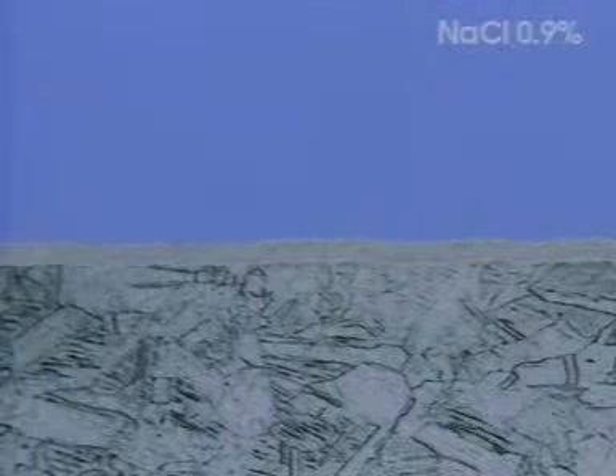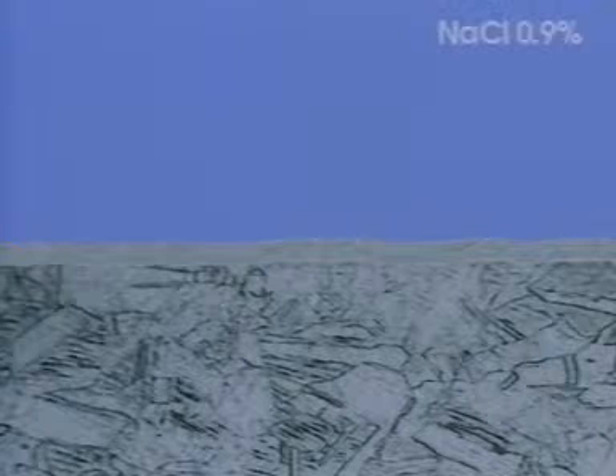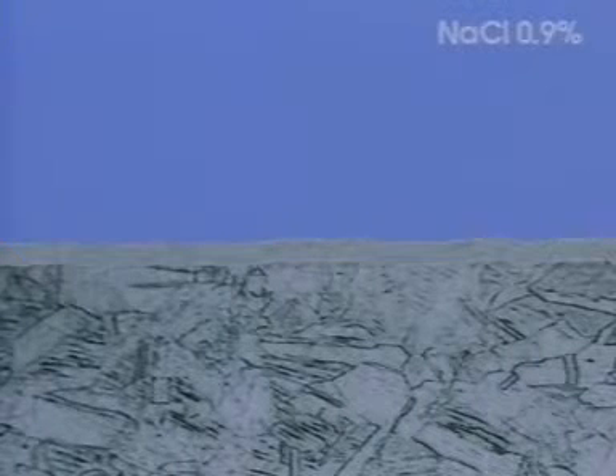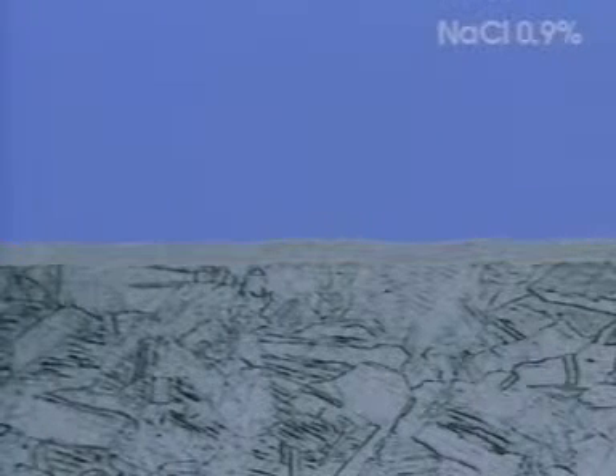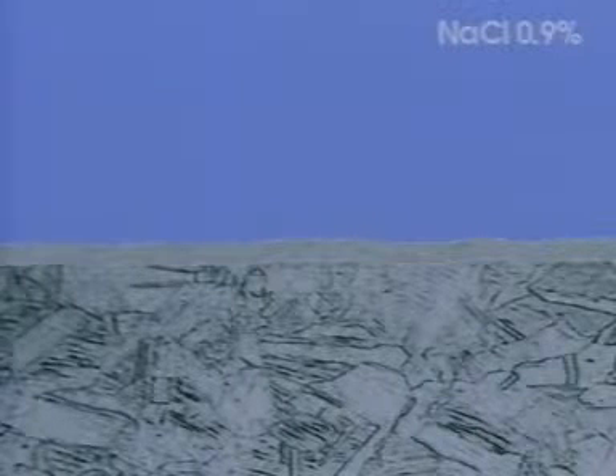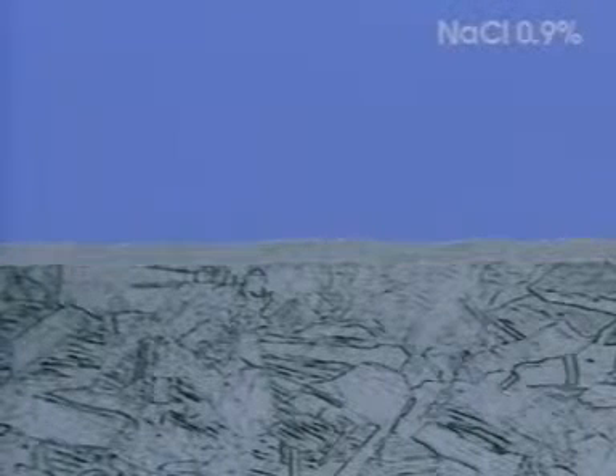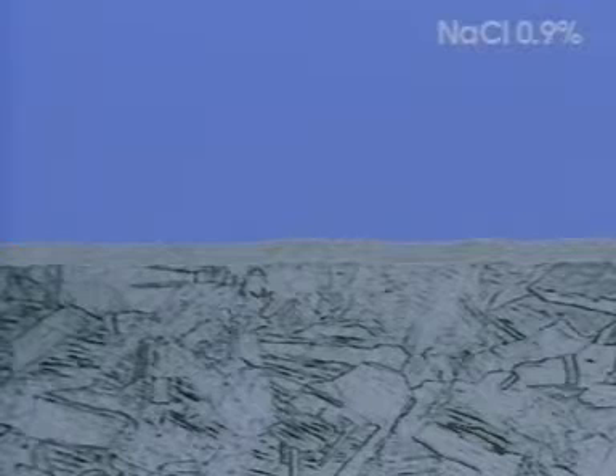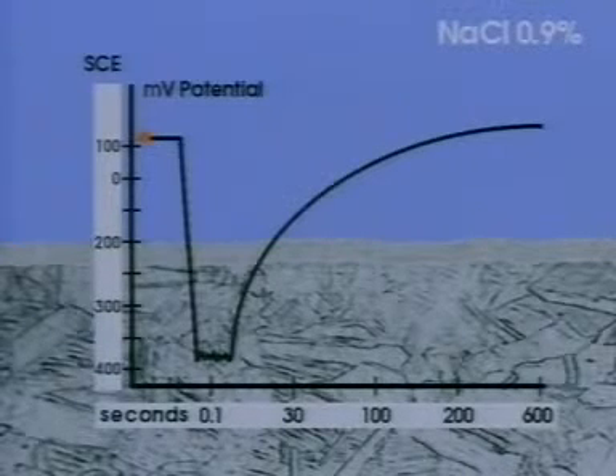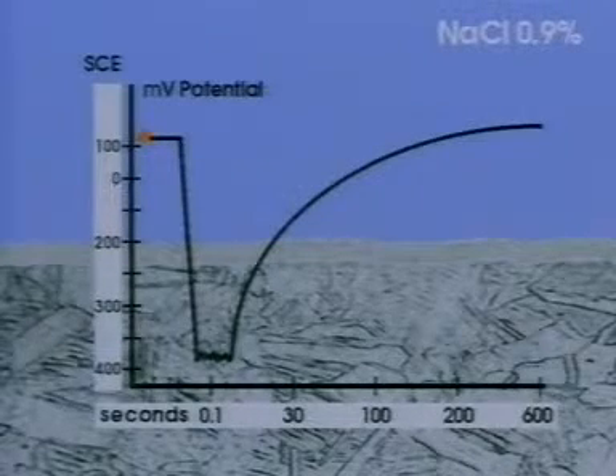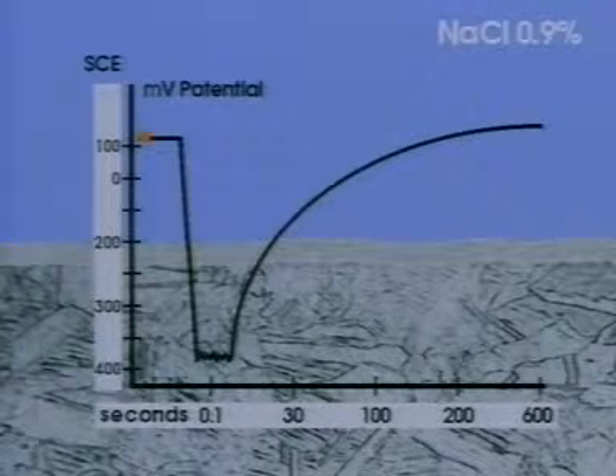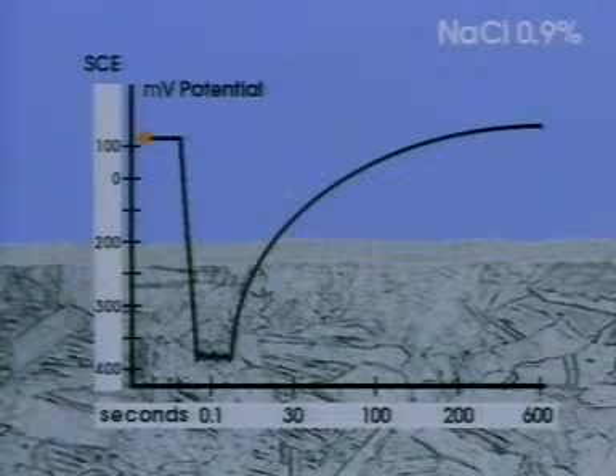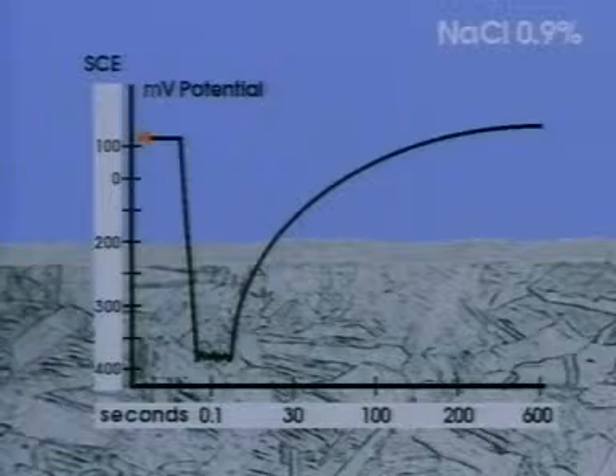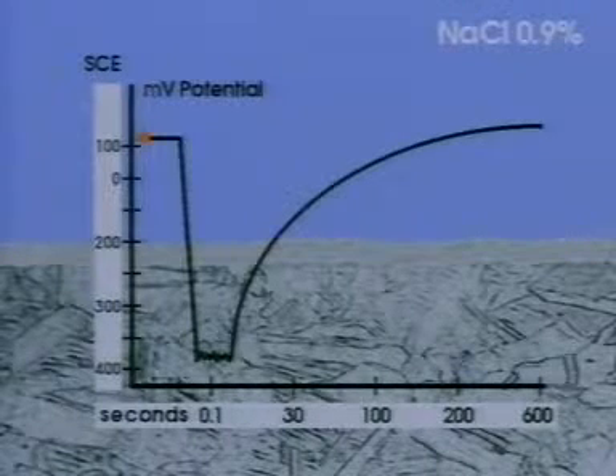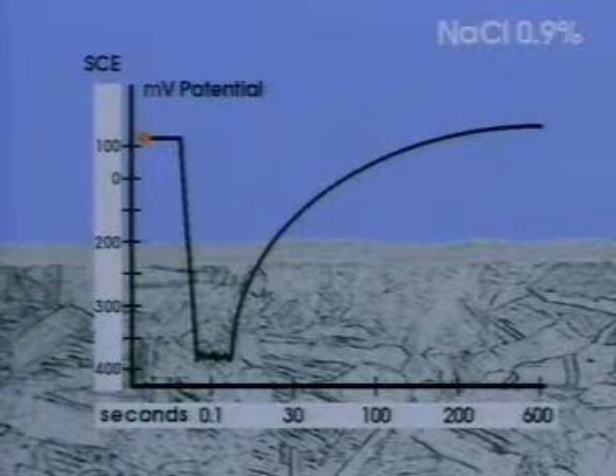On fully passivated stainless steel, due to the isolating properties of the passive layer, it is difficult for electrochemical reactions to occur. Overall reaction rate is very low. On any metal in an electrolyte, such as a physiological solution, we can measure the electrochemical potential, often called the corrosion potential. This indicates the state of the metal surface and can be easily measured. Passive surfaces have high corrosion potential.